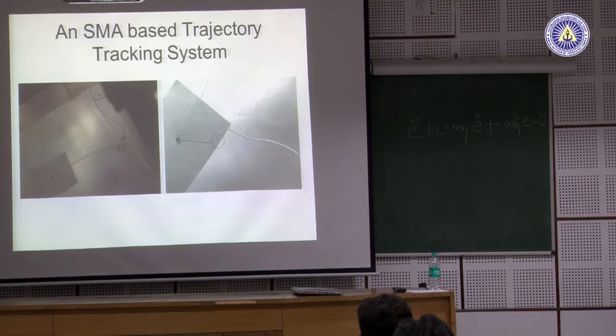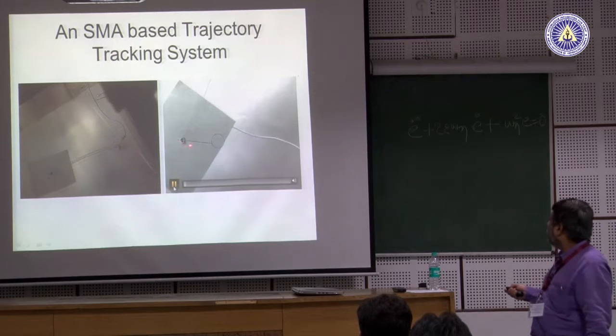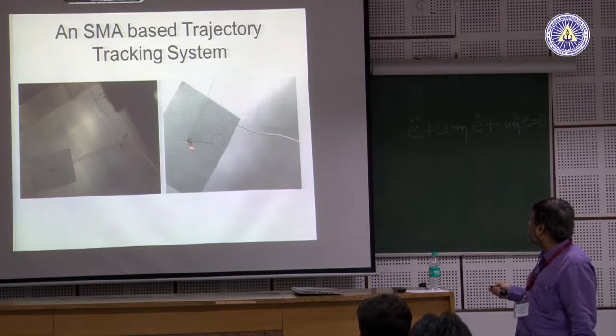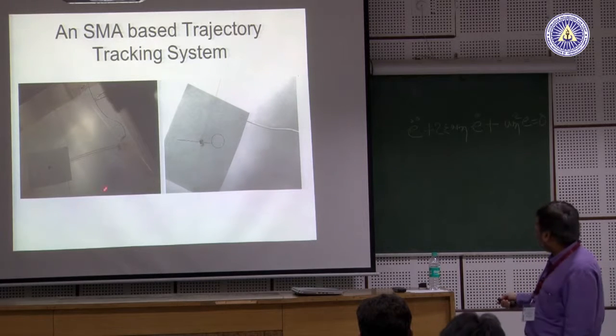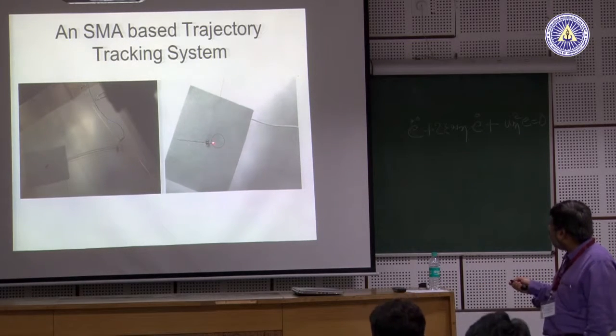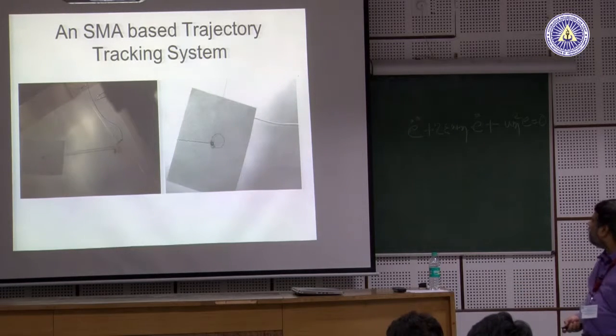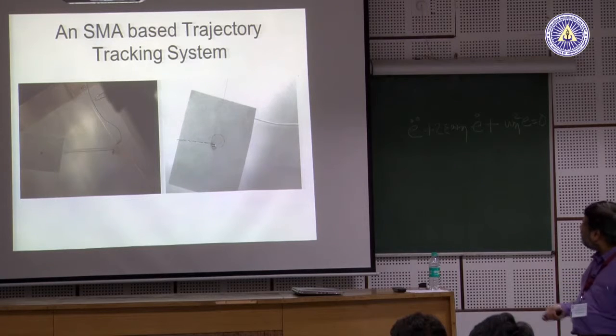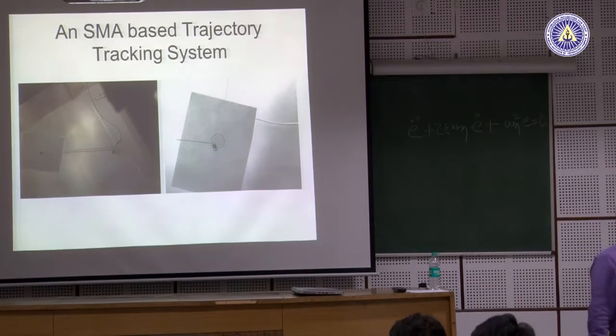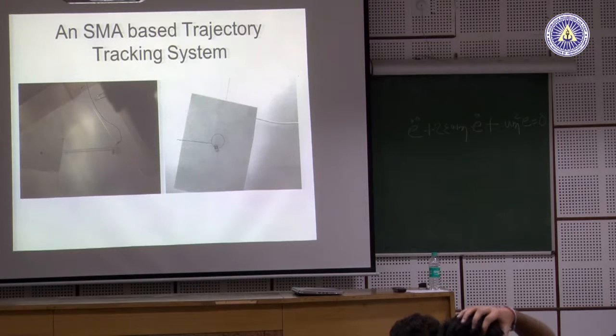And what happens side by side, I should have run this, is the tip. If you look at it, what is happening to the tip? That tip, I had given a difficult task, something with an infinite radius of curvature to suddenly a finite radius of curvature. So, by changing these muscle positions, it is actually following this particular pattern. Okay. And that is the challenge for a trajectory tracking system. And this is in ASME design, we have reported it, and with a plus minus 200 micron accuracy currently, you can actually do this in any two dimensional trajectory system. Okay.